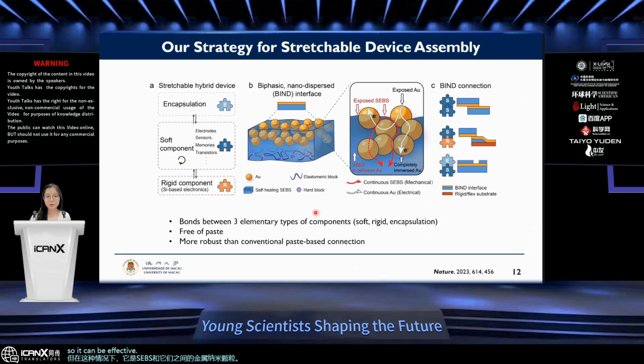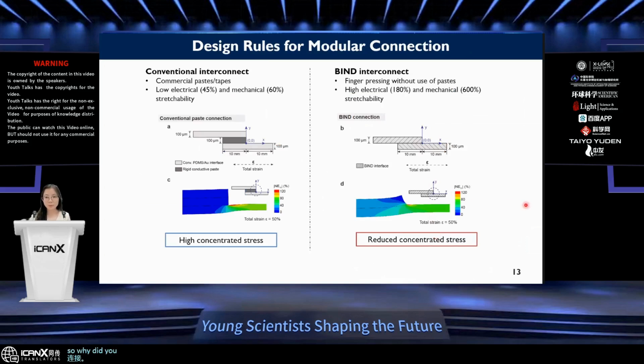So it can effectively bond between the three elementary types of components: the rigid one, the soft one, and the encapsulation one, because in this kind of interface there are both exposed self-healing polymer and exposed metal nanoparticles. It is also free of paste, and it has more robust function than the conventional paste-based connections. So why is the elimination of paste good for us? We can take a look at this kind of finite element analysis.